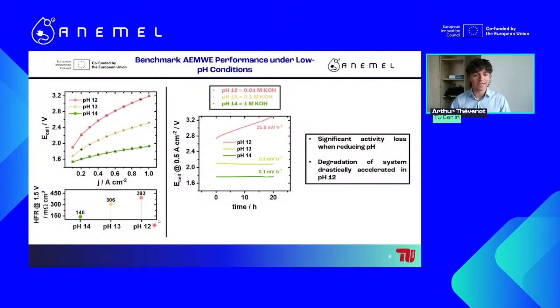What we see below now here is what is called the high frequency resistance. And these values are actually obtained through an electrochemical technique called potentiostatic electrochemical impedance spectroscopy. This technique allows you to deconvolute the different phenomena that occur in your system. But of course, it's difficult as the electrolyzer is a very big system with multiple layers and multiple interfaces. And therefore, it's always a bit difficult to deconvolute this when you have a two electrode setup, as we have here. And therefore, we stick to the HFR, and this HFR gives us the ohmic resistance of your system. So what is the electrical resistance for your entire system?